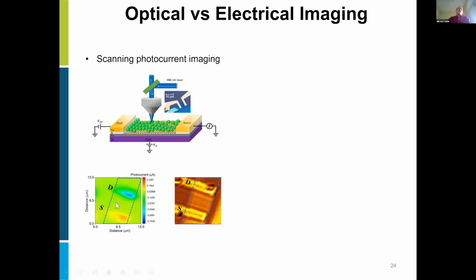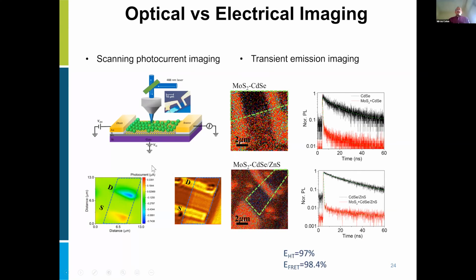Most activity is at the source and drain electrodes. This is a reflection image showing the device with the active area with the 2D material and the quantum dots here. We can take these devices and do transient emission imaging that will tell us how strong the interaction is between the quantum dots and the 2D material.